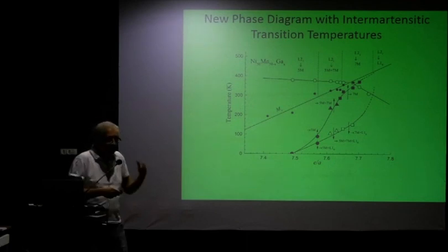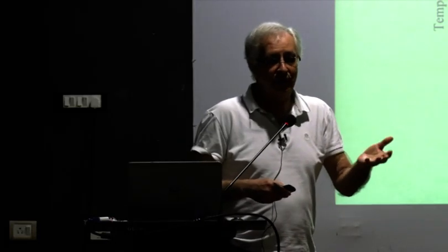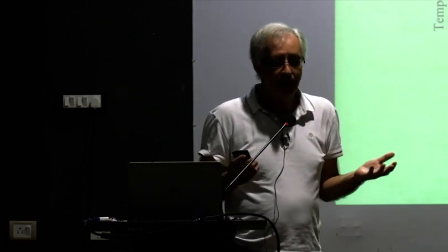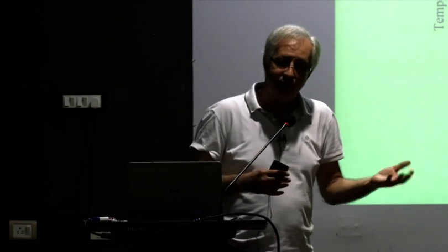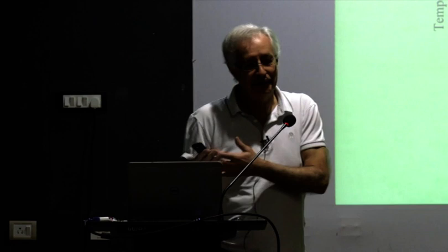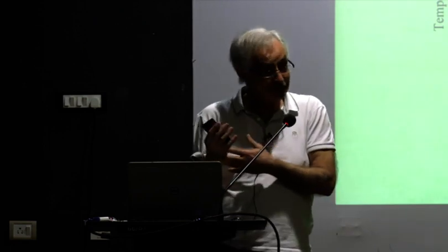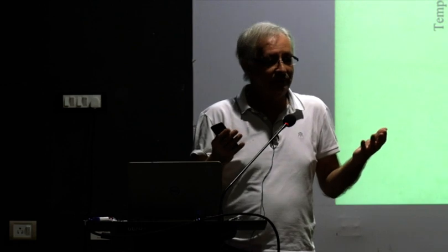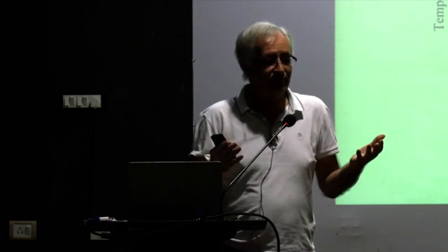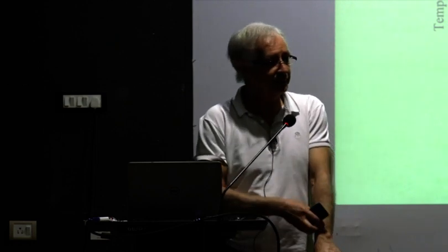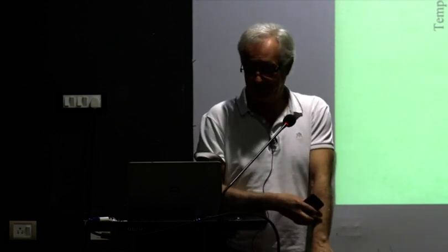From the L21, the thing wants to go into an L10, but it's trapped. It cannot, so it builds these structures. It's like magnetic frustration. It's the magnetic frustration analog for a lattice, to a certain extent. Yeah, the structure is under heavy strains and things like that in these modulated states, and once it gets into the L10, it's happy, if it can get in there.